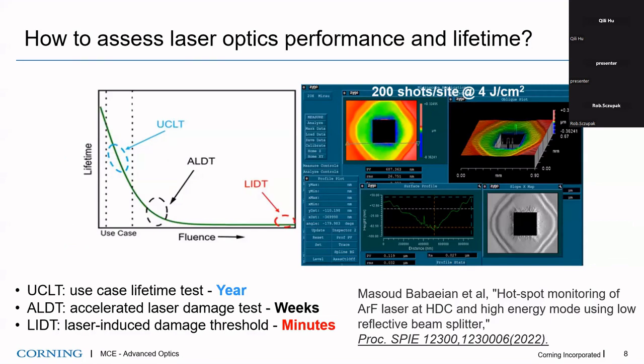So now we have been working continuously to improve the laser optics performance, and I try to figure out the best way to determine and improve the performance of the laser optics. On one side, we can get information from field returns or use case lifetime. And then we conduct ALDT, so-called accelerated laser damage testing, internally and work with our customers. And then we also conduct a laser-induced damage threshold test.